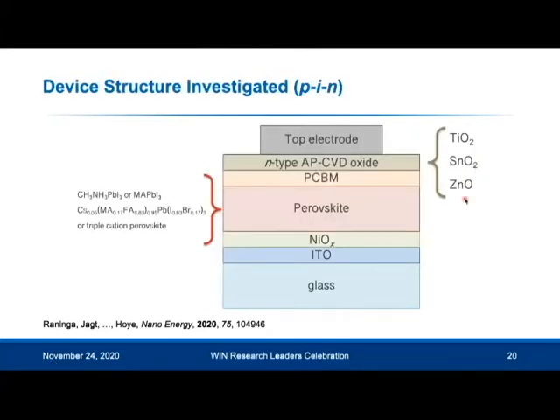the use of N-type oxides, and these were grown onto a PIN-structured perovskite solar cell. And what PIN means is that I'm using a hole transport layer on the bottom. I'm using an electron transport layer on top, which is PCBM. And I need to use an N-type oxide to grow an oxide buffer layer over this. So here I'm comparing 3 different N-type oxides, 3 different options. And these are titanium oxide, tin oxide, and zinc oxide.